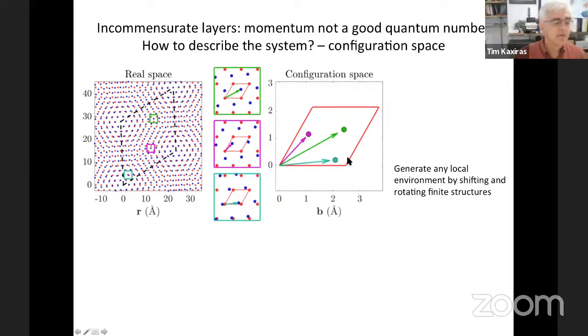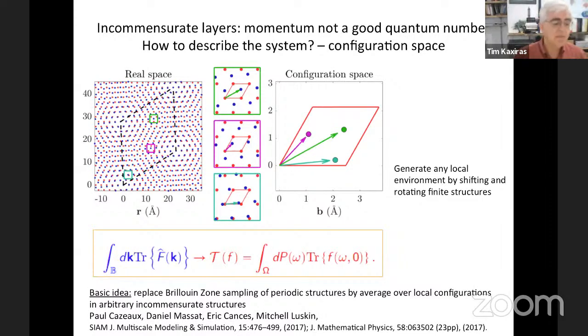This is very helpful, and we were at that time working very closely with a group of mathematicians who developed a very formal way to express this. Basically, you can go from integrals in the Brillouin zone in reciprocal space, which is typically what we do in physics to obtain observable quantities, to integrals over local configurations denoted by small omega over all the possible configurational space arrangements, which is covered by capital omega. So this description in terms of these local configurations can then give you a very accurate and mathematically exact description of the system.